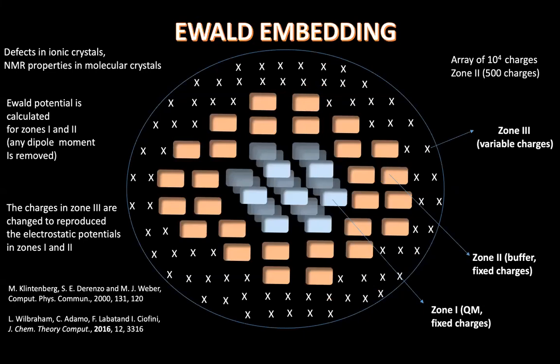These kinds of methods, essentially, what they do is start using a periodic boundary condition calculation where you can obtain the electrostatic potential in a particular cluster in your system. You can extract this cluster and you can select different regions within the cluster. For these three regions, in this case, you can do it in a different way, but this is one of the most common ways of doing it. What you do is change the charges of the third region of your system in a way that you are able to reproduce the electrostatic potential of the whole solid in the central region. In that way, you keep the description of the long-range interactions and you can still keep this periodicity of the crystal in a way. So we've been using these methods.